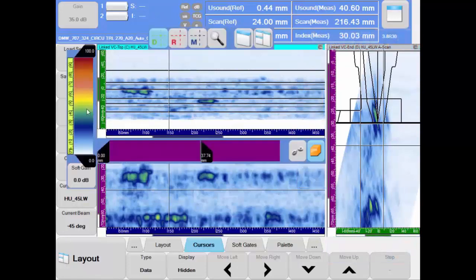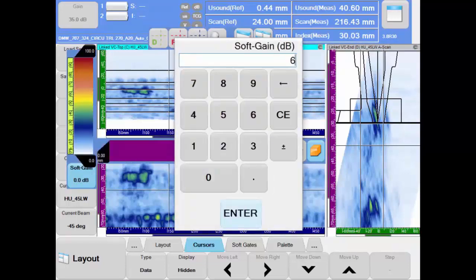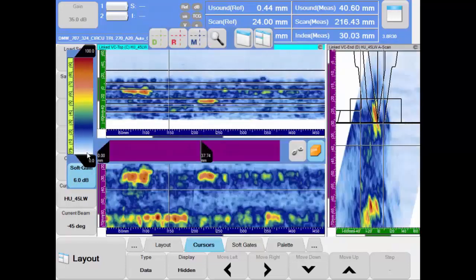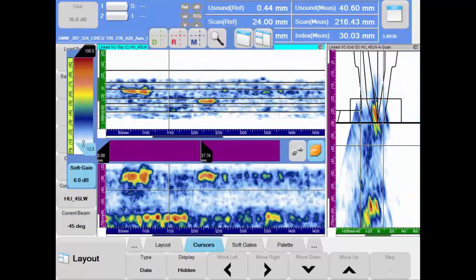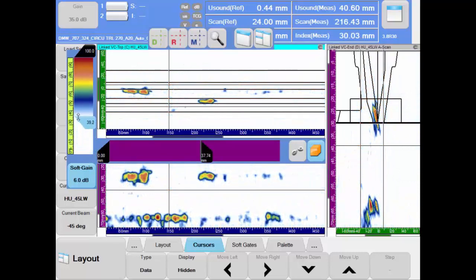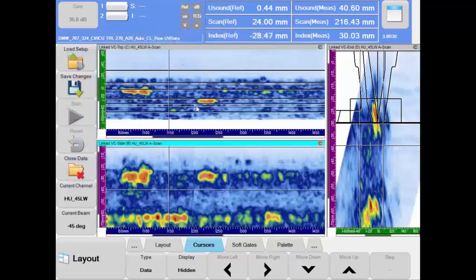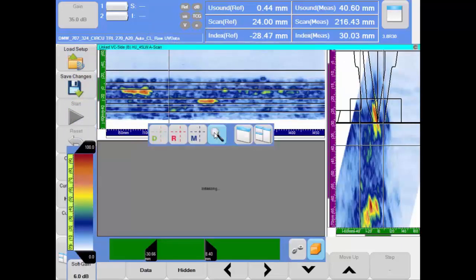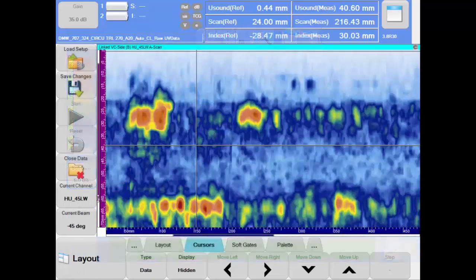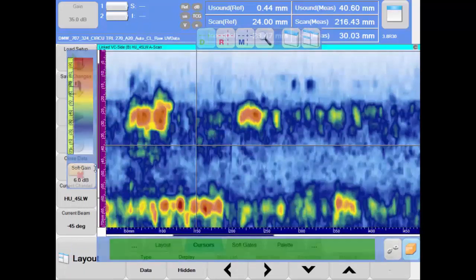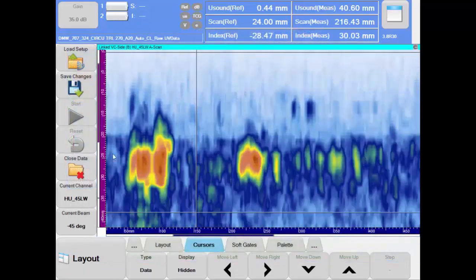A rapid evaluation of the signal-to-noise ratio shows around 10 dB, which is an excellent result for this type of weld. It proves that low-frequency L-wave beams can adequately propagate through the weld material and through various acoustic interfaces. Let's use the larger crack indication to illustrate the detailed sizing procedures for ID cracks.